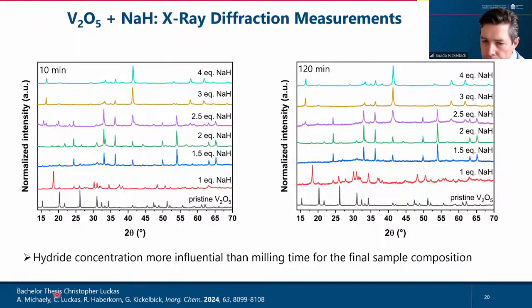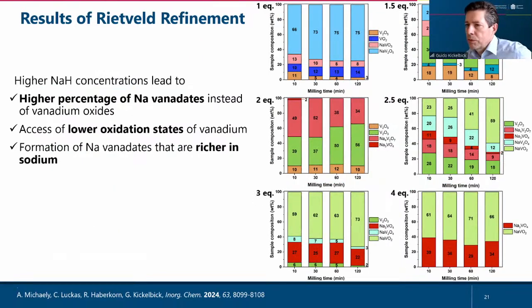And the question was now what was developing during this reaction. And this you can solve with Rietveld refinement. So what you see here are the different amounts of the hydrides, from 1 equivalent to 4 equivalents. And what you see is at the beginning, you have a strange composition of different oxides and reduced oxides. And at the end, you form only 2 different sodium vanadates. So it seems that you have here a very similar effect. You have a reduction of the vanadium, and in addition, you form an intercalation of the sodium.